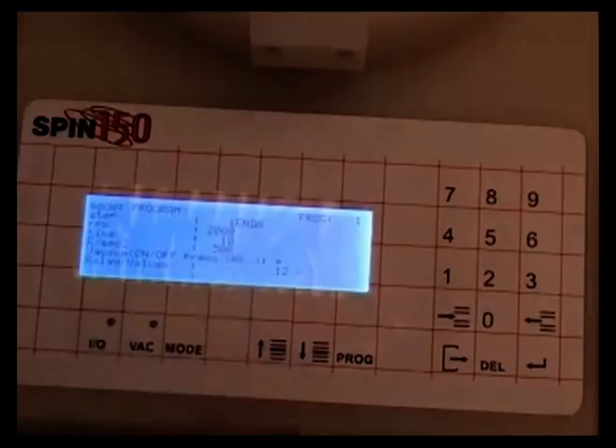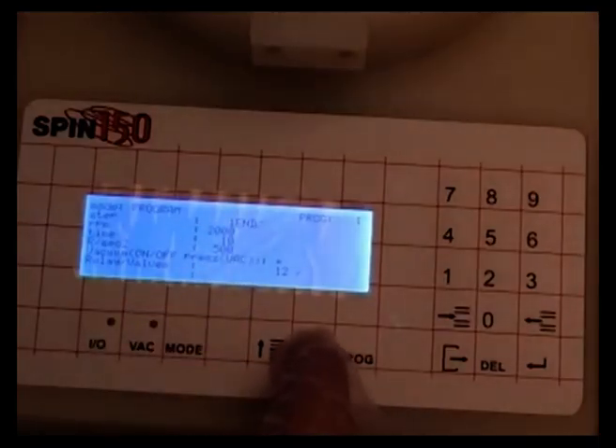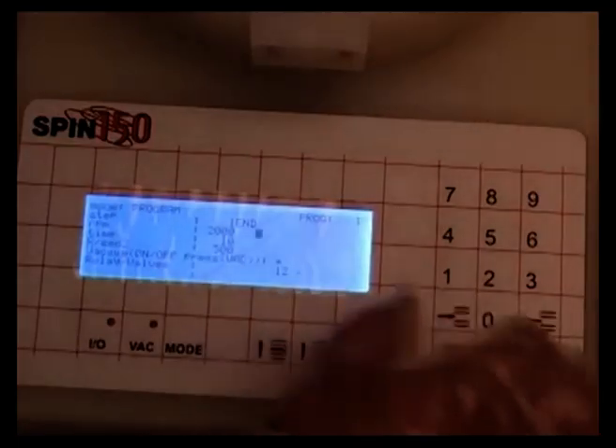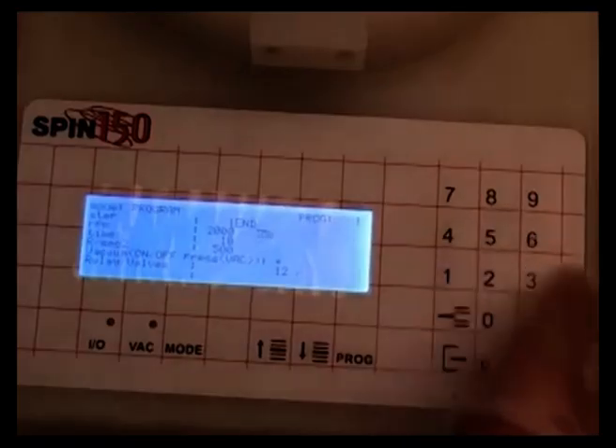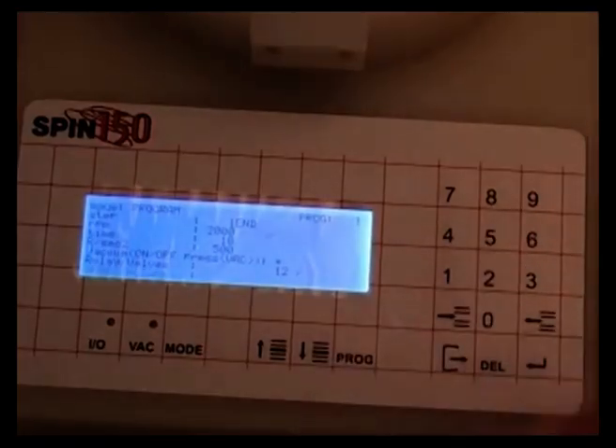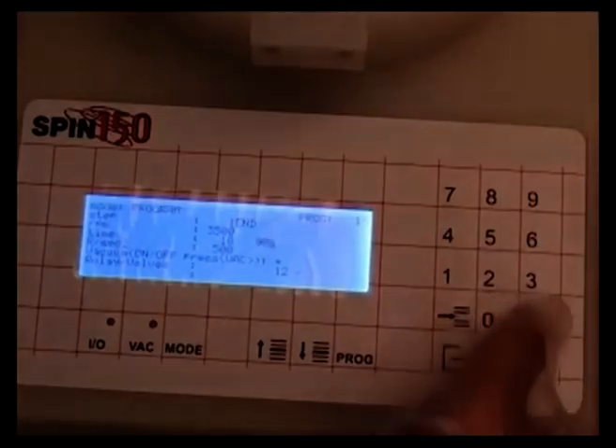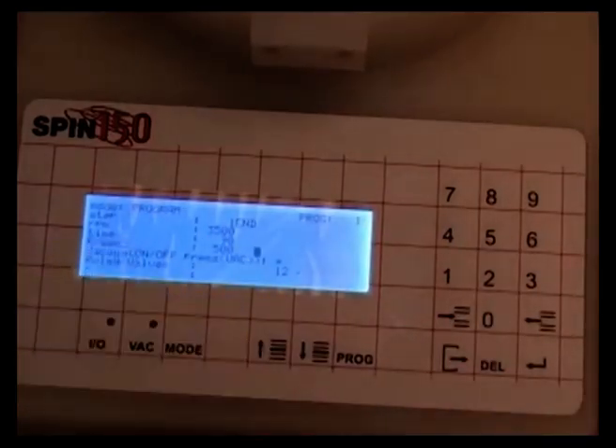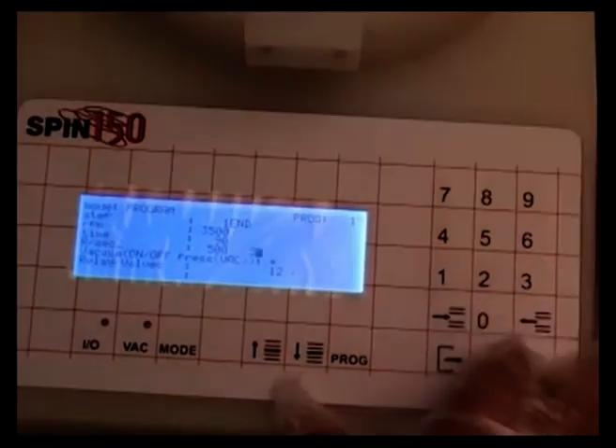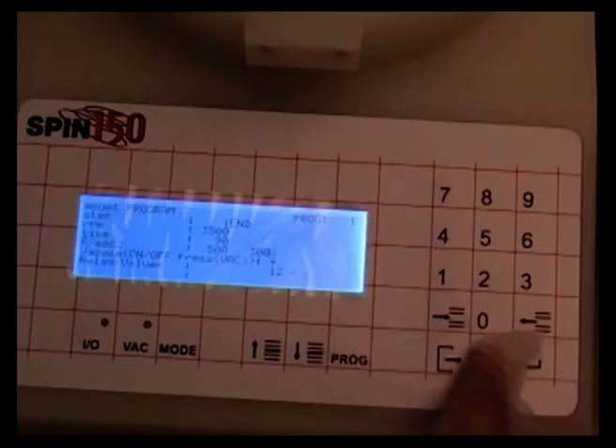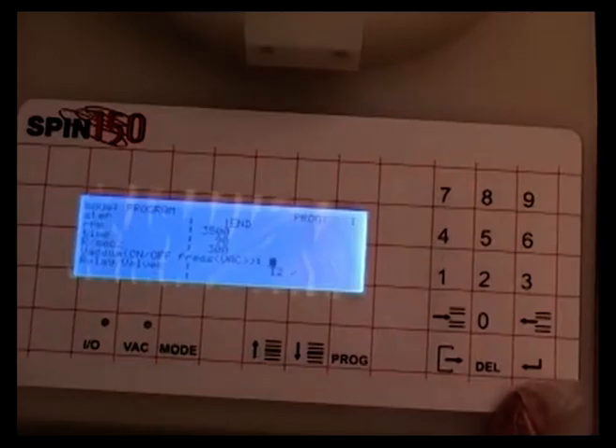So it's one end. Now we move to the next option here, and we get this RPM, which is 2000 in this particular case, as you can see. So what I'm going to do is change this to 3500, which is our requirement, and hit enter for the system to take this. The time for which we need to hold this RPM is about 90 seconds, so we enter 90 here. The next step is the revolutions per minute per second, the acceleration. So we put the value 300 and enter it. For our condition we need the vacuum to be on while the spinning is happening, so we just take the default, and that completes the program.